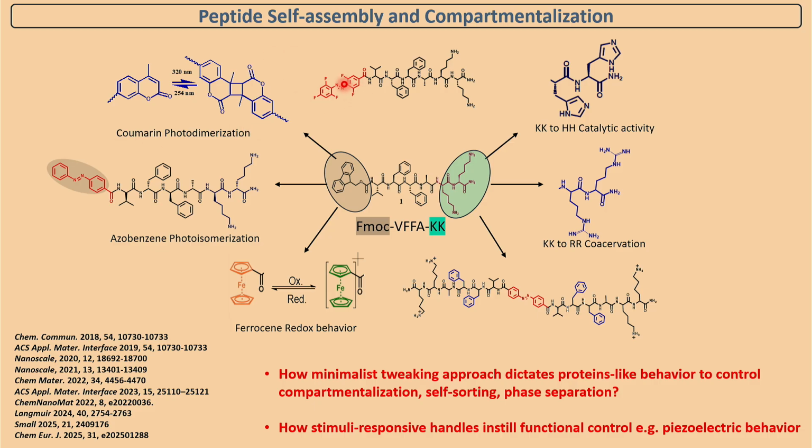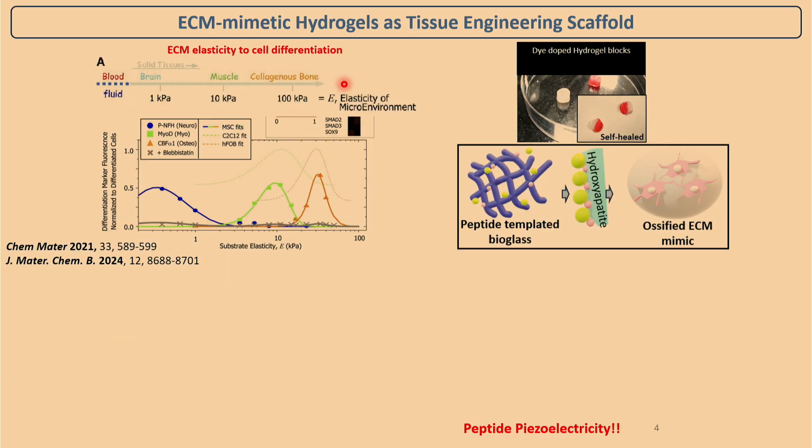If you have fluorinated azobenzene, you can make this photoswitch, which is a visible photoswitch, which is very good, because if you have a visible photoswitch and you make hydrogel out of it, you don't need to shine UV light over your hydrogel, so that the hydrogel will have its gel-sol transitions without such harmful UV light. You can do it in visible light. That has an implication in photopharmacology. I have 2 slides to show why it is important later on. So this is another thing.